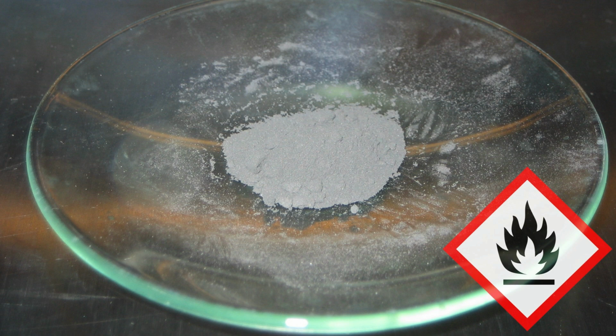The formation of sodium aluminate, NaAl(OH)4, requires that solutions of high concentration of sodium hydroxide are used in order to avoid the formation of aluminum hydroxide, which precipitates as bayerite. Hence sodium hydroxide solutions with concentrations of up to 5 molar are used. Bayerite may cause blocking of the pores formed during leaching, and with a subsequent loss of surface area, it can reduce the efficiency and activity of the catalyst.